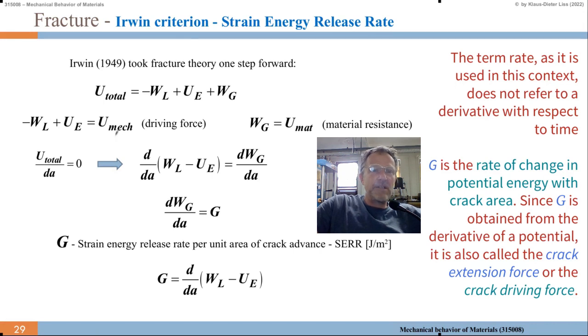So we have a driving force: the mechanical energy has to balance the workload and the elastic energy, and then the total derivative of U over dA has to become zero for the equilibrium condition, or the critical A. We work it out: dWg over dA equals G, so it becomes a constant G.